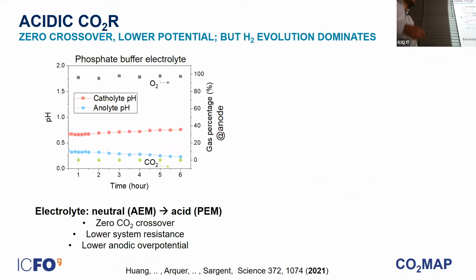Okay, so we went into the lab and we looked into this. We monitored the pH and the gas percentage at the anode side of the reactor. If you remember, the problem was that CO2 was converted into carbonate, was crossing the membrane, and was then converted back into CO2, wasting energy.